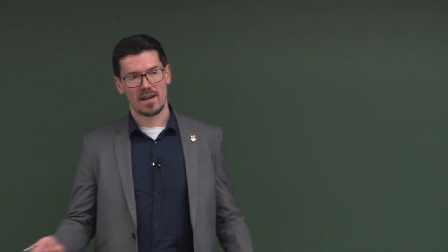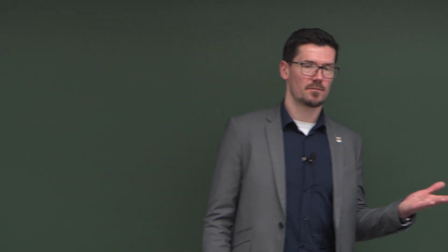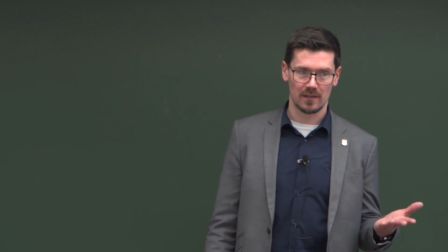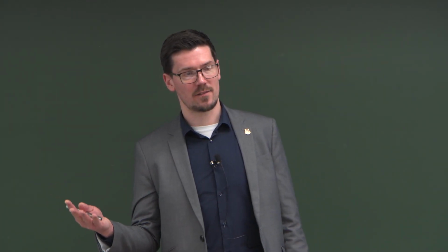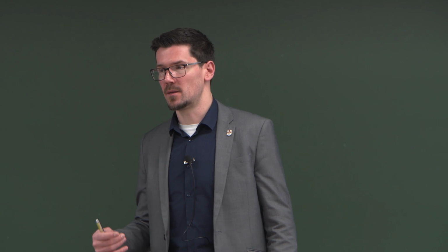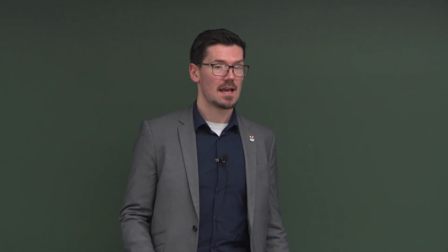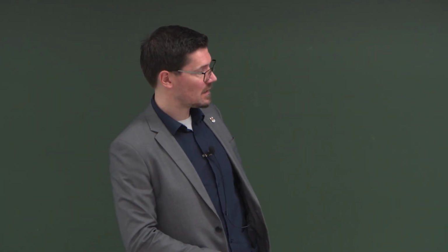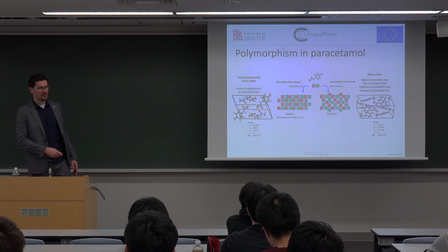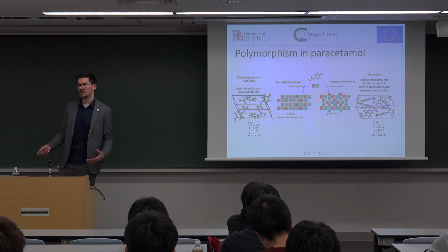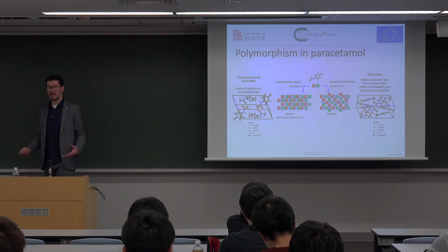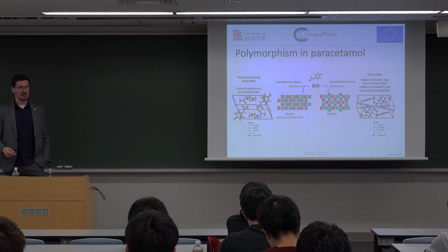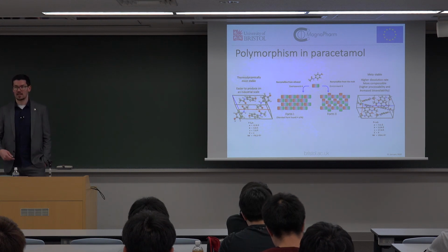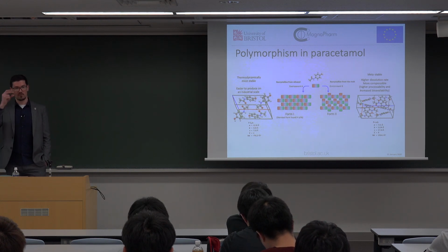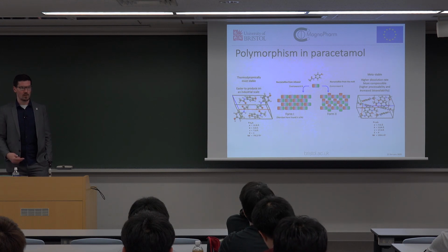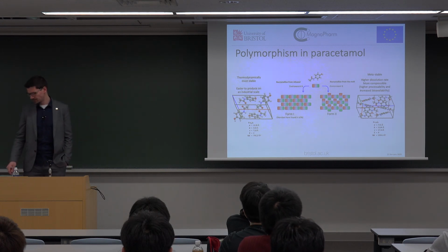However, the trade-off is, do you invest lots of money into heating up lots of paracetamol to melt it, or do you just recrystallize it from ethanol and accept the fact that it's going to be slightly less efficacious? In this case, the heating is too expensive, so Form 1 is always the one seen in tablets. The only time you're going to see it in tablets is if someone comes up with a room temperature, room pressure way to make Form 2 without lots of hassle or toxic chemicals or additives.